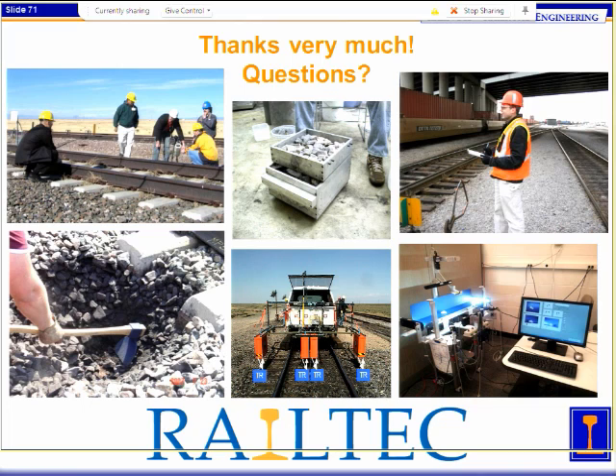All right. So the question was about the fouling content indices. I think you said, let me make sure I got the question right, because you have seen fouling index more often, correct? I believe fouling content is mainly used with regards to undercutting operations, because the undercutting ballast cleaner scoops up the ballast underneath the track, washes it, sieves it, and puts it back in track. What they sieve is the passing 3/8 inch. That's what fouling content is. If you put that through an undercutter, that percentage, I believe, is roughly what you would get rid of during the cleaning operations. I believe that's where the origin of that specification or index is. Many people just consider anything below 3/8 of an inch to be not useful ballast.